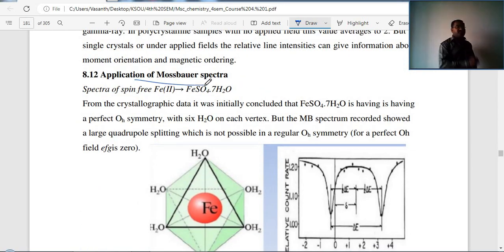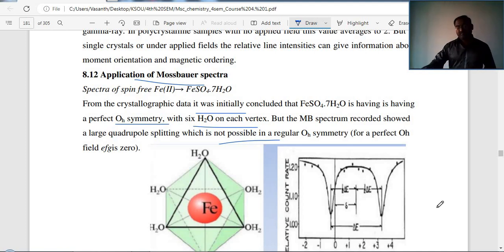What are the applications of these Mossbauer spectra? Yes, high spin ferrous sulfate. From the crystallographic data, it was initially concluded that the hydrated ferrous salt has perfect octahedral symmetry with 6 water molecules, one at each vertex. But the Mossbauer spectrum recorded showed a quadrupole splitting, which is not possible in a regular octahedral field.